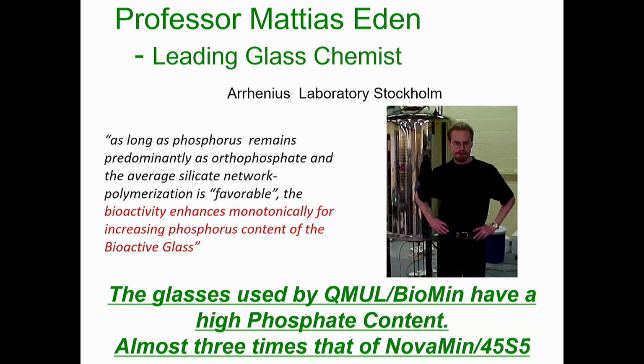I've worked closely with a chap called Professor Mattias Edén, based in Sweden in the Arrhenius Laboratory, and this is a quote I've taken from one of his papers. He says, "As long as phosphorus remains predominantly as orthophosphate and the average silicate network polymerization, which I would term network connectivity, is favorable, the bioactivity, in other words the apatite formation, increases monotonically for increasing phosphorus content of the bioglass."